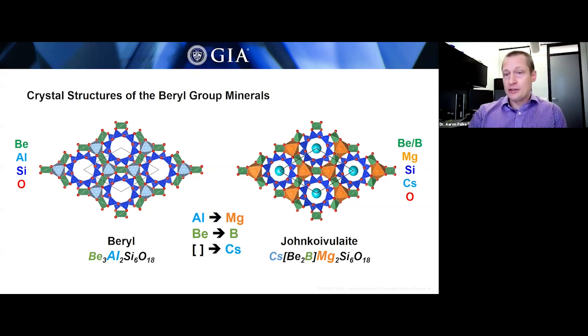Johnkoivulaite's a little more complicated. You can see when we go to johnkoivulaite from beryl, we have to make a few more substitutions. So we're substituting magnesium in johnkoivulaite for the aluminum in beryl. We're substituting some boron for some of the beryllium in that distorted tetrahedral site in beryl. And we're also adding an atom to this channel site in between those silica rings.